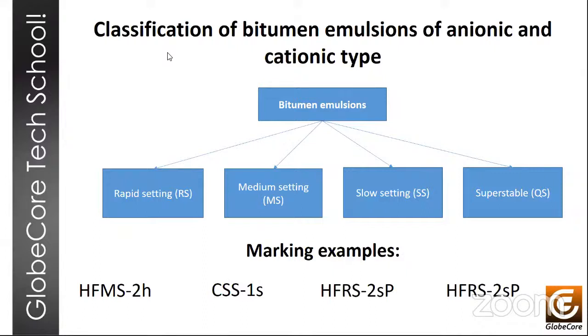The next parameter is the viscosity of the resulting emulsion. It's indicated on a relative scale, either 1 or 2. The number 2 indicates that the emulsion is more viscous than the emulsion with index 1.